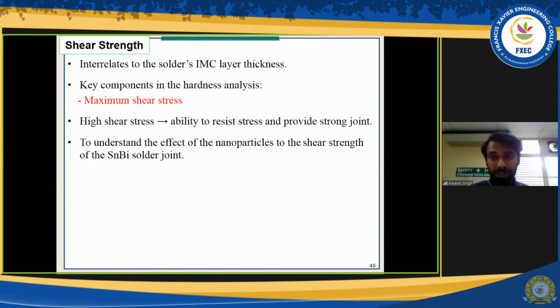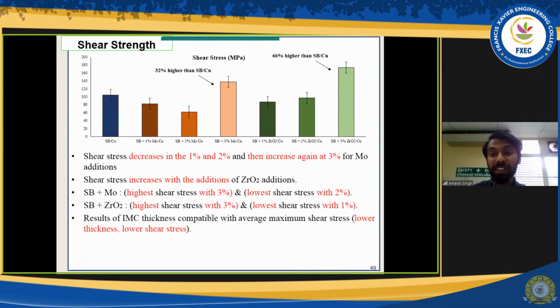Let me go to what we could say is the important part of a solder alloy, the strength, or the shear strength of the solder alloy. So we can see here the shear strength is done basically by using a single lap method. 1% and 2% for both cases had a lower shear strength than the SnBi, but it was more evident in the 2% of molybdenum, because with 2% of molybdenum, even though the presence of molybdenum is very high at that point, the production of a very thin IMC layer could not actually support the stress.